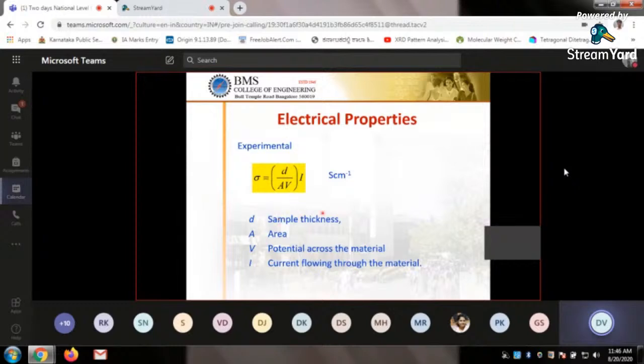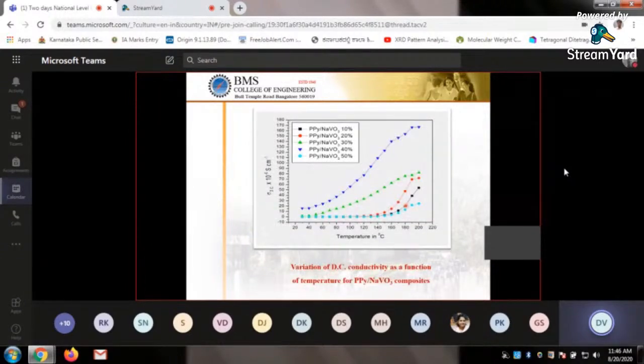So how are we measuring electrical properties? If you know the sample thickness d, and then the area of the sample. If it is circular, you can use pi r squared to get the area, and if it is square, use length into breadth. You will get the area, and then V is the potential across the material, and I is the current. So we are applying current and measuring voltage. If you know current and voltage, you can calculate conductivity. So we are using that instrument. We are measuring the conductivity of different materials at different temperatures, at different compositions.